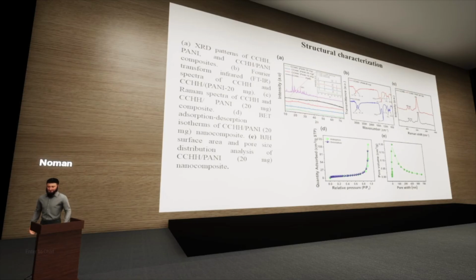Similarly, FTIR analysis was performed to find the functionalities of the nanocomposite, and to compare the D spacing and the G band of the material, Raman spectra of the nanocomposite were also recorded. To find out how porous the material is and how much charge it can accommodate, BET analysis was performed, and these two graphs show the BET analysis of the material.